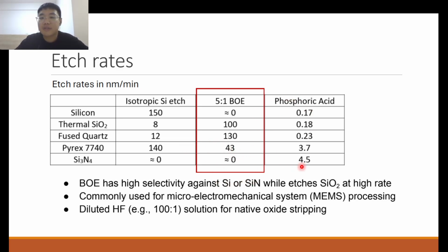And if you see, phosphoric acid is different. It's a very selective etch for nitride. It etches nitride at this 4.5 rate, as for silicon and oxide, at a much lower rate. So phosphoric acid is a good selective nitride etch.